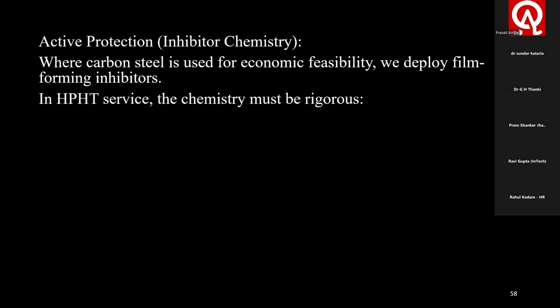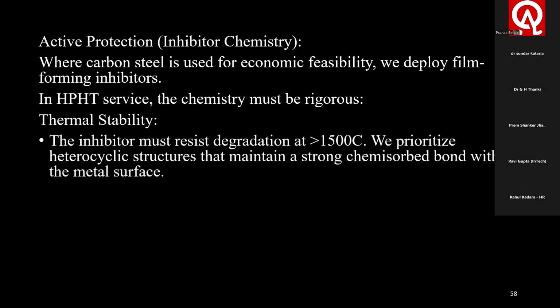Active protection, like inhibitor chemistry. When carbon steel is used for economic feasibility, we deploy film forming inhibitors. In HPHT service, the chemistry must be rigorous. Thermal stability, as we have seen in the previous slides: the inhibitor must resist degradation at 150 degrees centigrade.